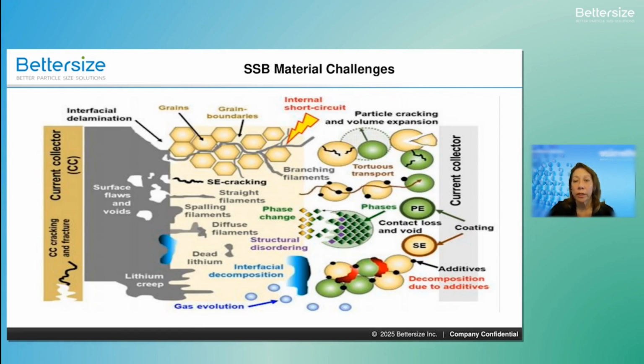Material compatibility: we often have mismatches between the electrodes and the electrolyte. This can occur with cathodes, which can often react with the sulfide or oxide electrolytes, and lithium metal can form unstable interfaces with many solid electrolytes.